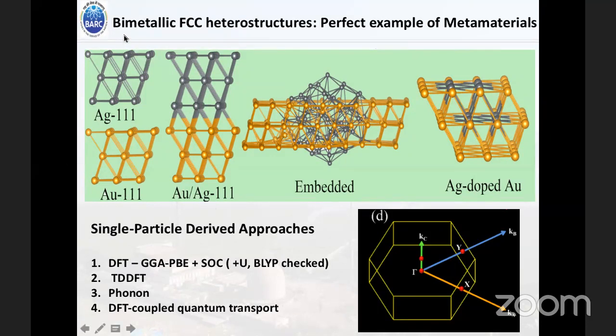Okay. So these are the bimetallic FCC heterostructures, which are a perfect example of metamaterials, when two different kinds of materials are combined together and give some very different properties. So what we have done is we have tried the Ag111 surface, Au111 surface, and Au-Ag large area interface, and then embedded nanostructure, and then Ag-doped Au nanostructure. All of them belong to a hexagonal Brillouin zone. And in the next slide, I will be showing the band dispersion along this path, gamma X, Y, gamma.